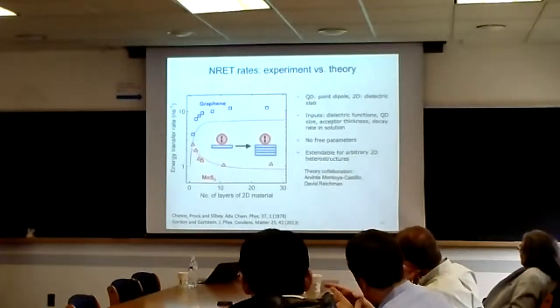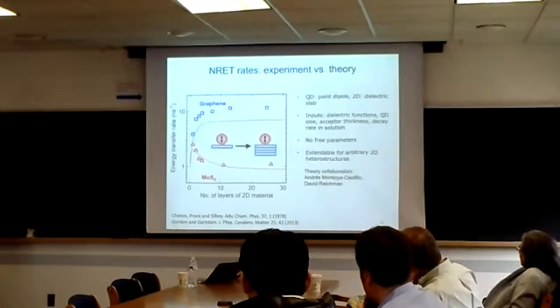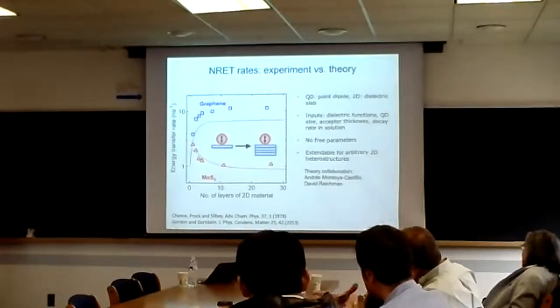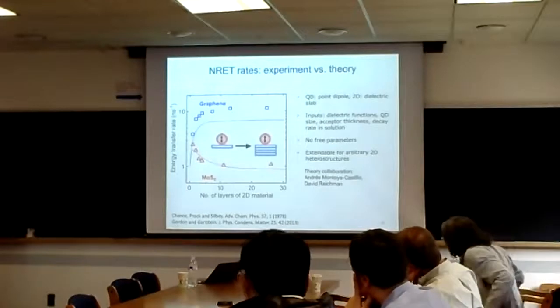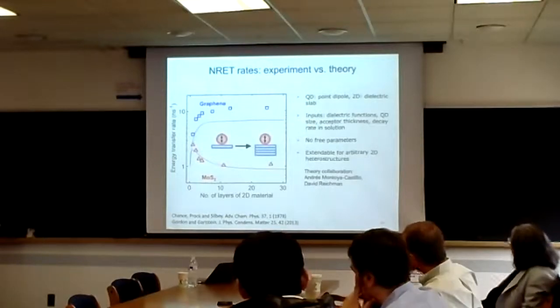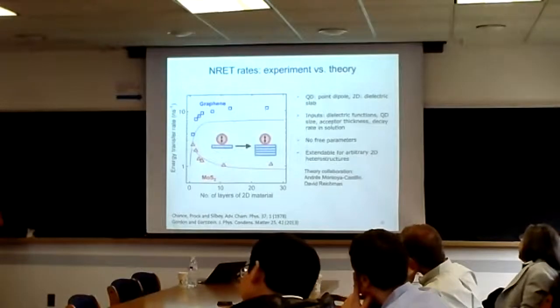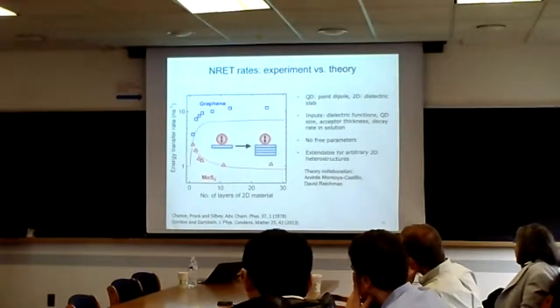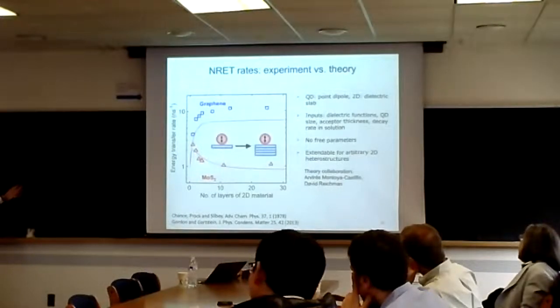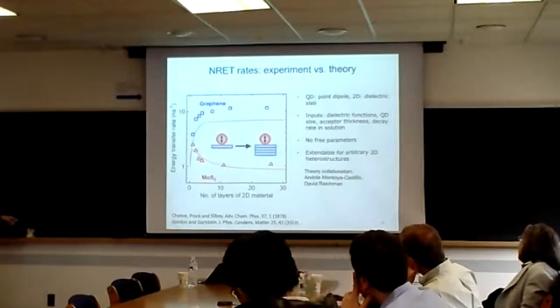Can you compare this in the context of a Purcell enhancement of the decay rate, or something in a cavity? Yeah. When you're changing the epsilon, you are changing the radiative rate as well, and that's not as strong an effect here as the change. So for all practical purposes, this dramatic change in the energy transfer rate is not due to any Purcell enhancement. We include that in the calculation. It comes in as just this effect of epsilon.